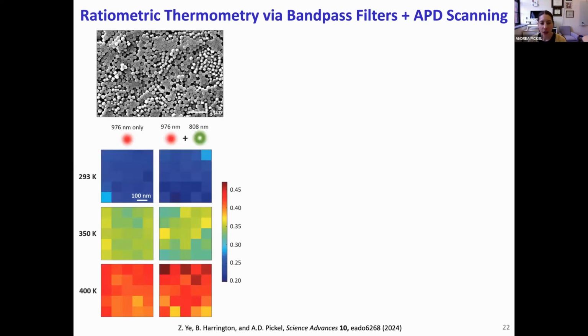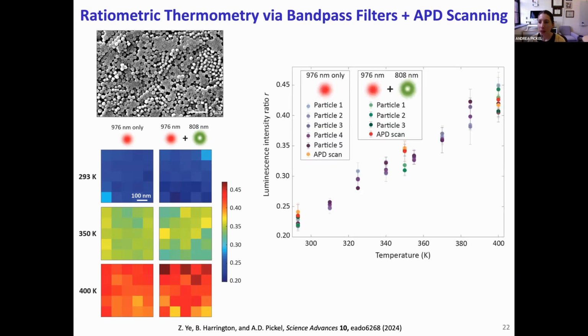As a final validation step, we perform similar APD scans at uniform temperatures in both diffraction-limited and STED modes, in this case on a UCNP multilayer, primarily consisting of double-layer regions, just to boost our signal to noise. We can then overlay the mean ratio and standard deviation from the APD scans at each temperature in both modes on our prior spectroscopic data, and we again get an excellent match.